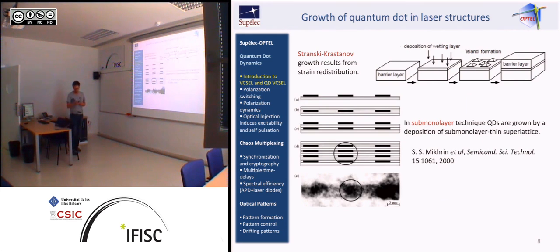Roughly speaking, there are many techniques, but these are probably the two most important ways to grow these dots. You have to do this artificially; they don't come naturally. To my knowledge, the first technique suggested was in fact found by luck, because if you want to grow a semiconductor laser, you have to be careful about lattice matching. Some people, especially those working on VCSELs quite a long time ago, understood that if they wanted long wavelength VCSELs, that was a big problem, because the active medium was not lattice matched to the mirrors.